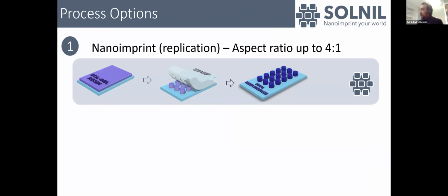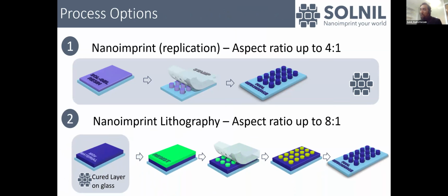although you see some publications about direct nano-imprint of high aspect ratio, I think the easiest way, and what most of the industry is doing today, is to use traditional top-down etching approaches, which are used today in the semiconductor industry or with microelectronics. And what we propose there is just to replace atomic layer deposition or PECVD by a coating made by spin coating to reduce the cycle time. And then you can use your standard process based on nano-imprint lithography or deep UV to etch this layer.